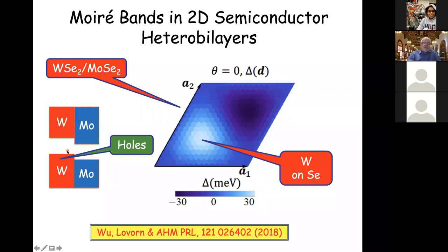So in this particular case, if you look at the band structure of these two-dimensional crystals, you will see that they're semiconductors. And what I've drawn here with an energy axis vertically is the energies at which there are states in the band. So this energy is the top of the valence band in the tungsten diselenide, bottom of the conduction band. And you can see here the so-called type 2 band alignment, where the bottom of the conduction band and top of the valence band are localized to good approximation in different materials. I'm just going to talk about the case of holes in the system. So the holes in the top of the valence band, if you remove some carriers from this 2D system, for example, using gates, the holes would be located in the tungsten diselenide layer.